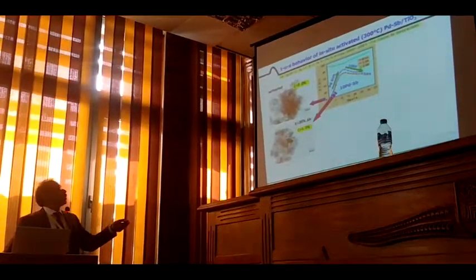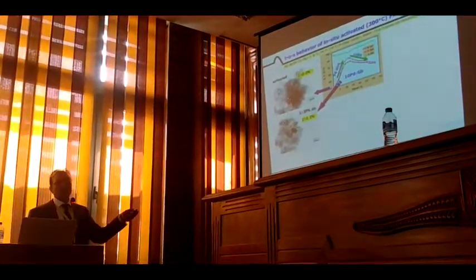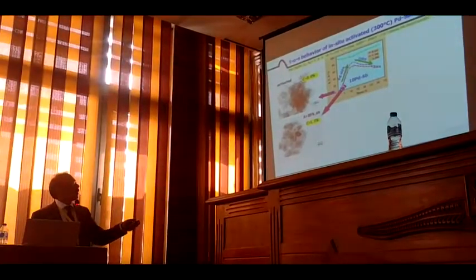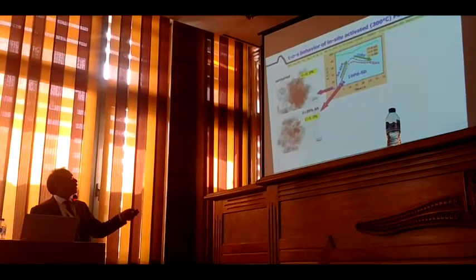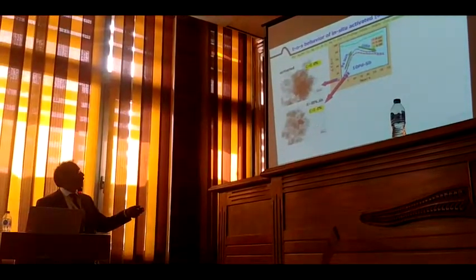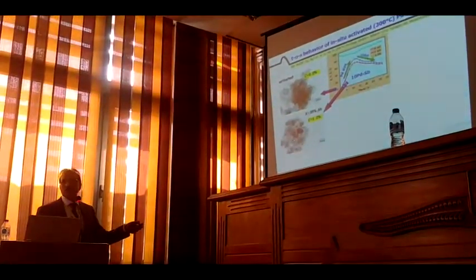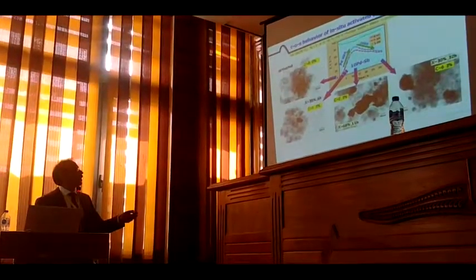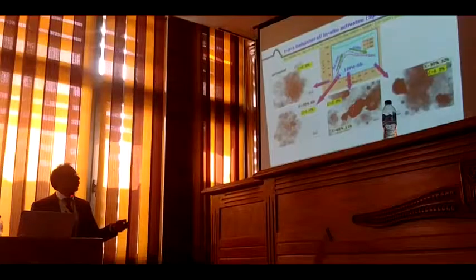So the fresh catalyst has very small palladium particles, you can't see them. And coke is also not there, just air calcined. If you go after 6 hours, the conversion increased to 35%, and the coke is also increased. And the palladium particles begin to grow. If you look at the electron micrographs, the maximum active sample and the deactivated one, the coke is further increased from 1.2 to 2.3, and the conversion increased from 35% to 68% after 11 hours. The particles also become 50 to 100 nanometers.